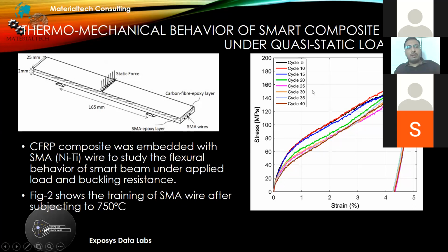Now, the 2 millimeter thick strip specimen we have used, before embedment, we have gone through different cycles of training. That means we have trained it to memorize the shape in different cycles, and it has proved that it has given the optimum cycling. The red color shows the high stress carrying capacity. The high recovery stresses can be achieved in the 10 cycles, and the lowest in the 25 cycles. So that's how we have optimized the cycling of the training.